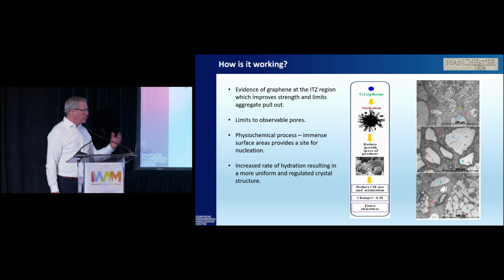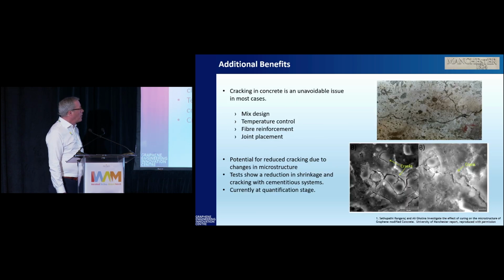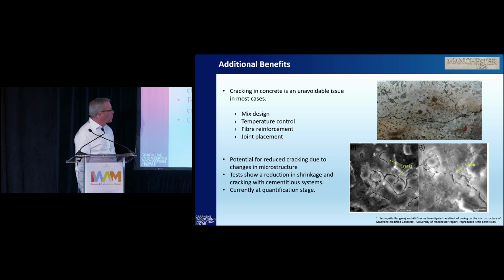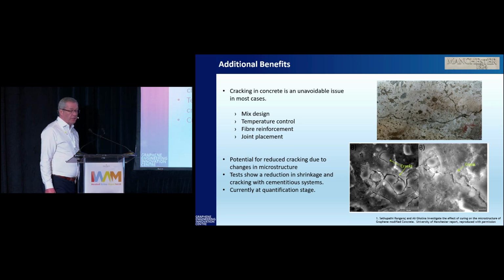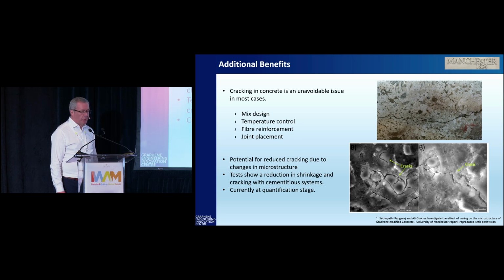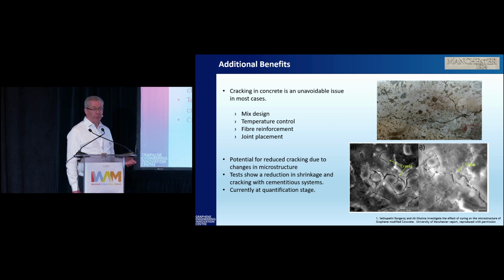But the mixture of the graphenes, and we're managing to disperse it into the fluids and using the liquid-based systems, we're getting very consistent results. We don't get those consistent results with the dry systems at the moment. There are other benefits. These are not fully quantified at this moment in time, but with all concrete systems, you do get shrinkage. It's just part of the natural design of the system. You can't get away from it. But certainly what we have shown is the microstructure does change, and we do get reduced shrinkage. And then when we start doing water ingress sampling, we can actually improve concrete. So we can start to tune the concretes for different applications. It's not been wholly quantified at this moment in time. But again, using the high selectivity of the materials, we can get significant improvements in here as well.